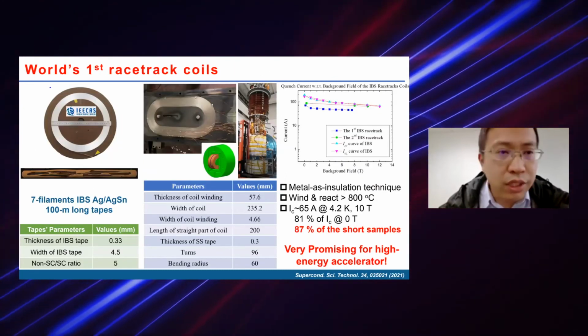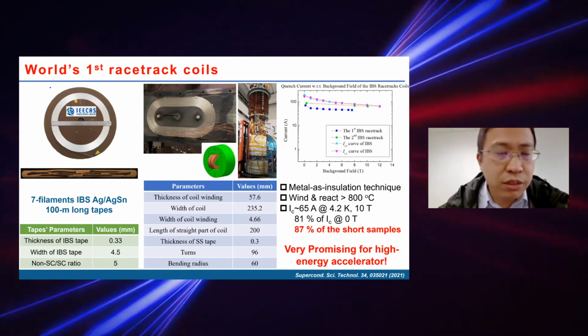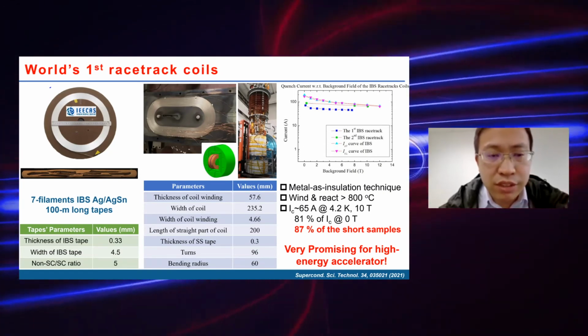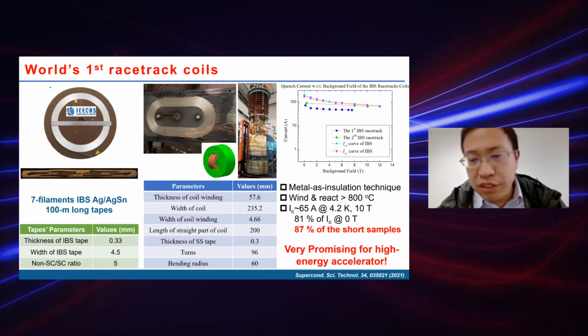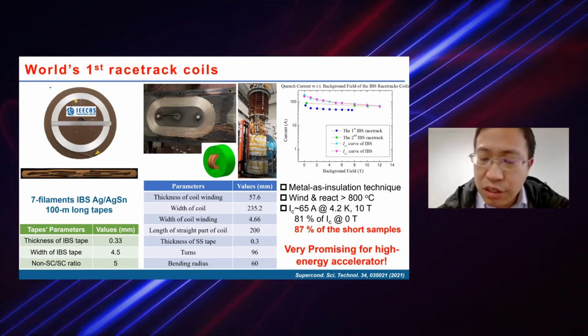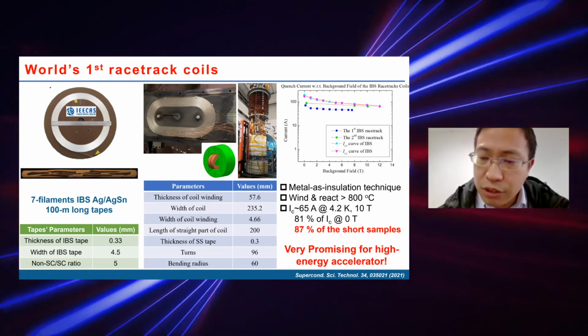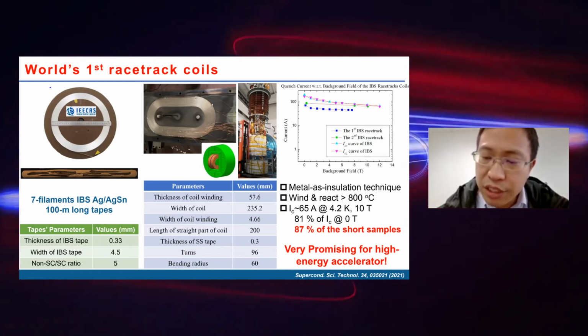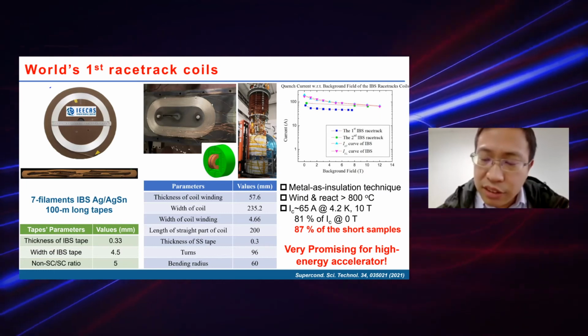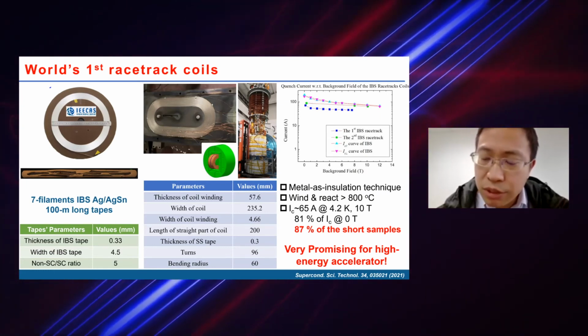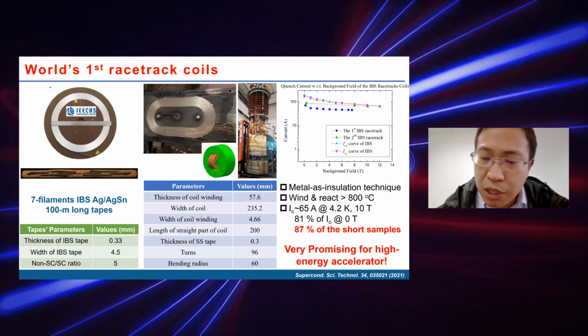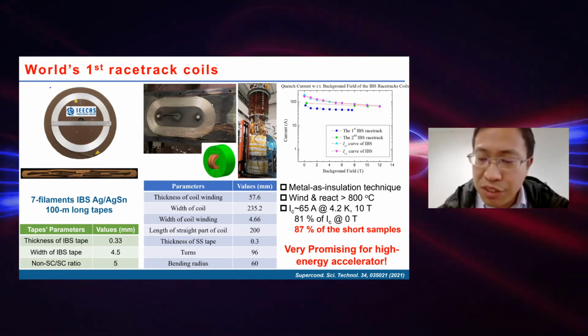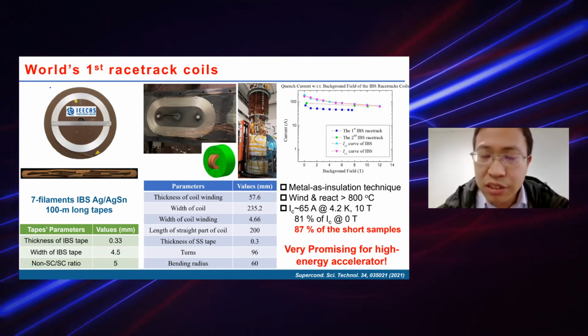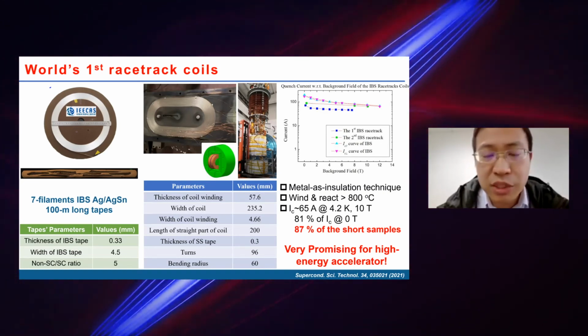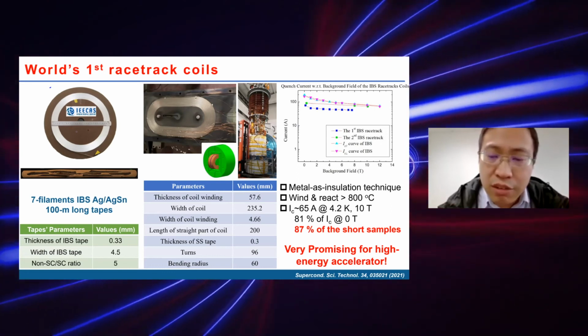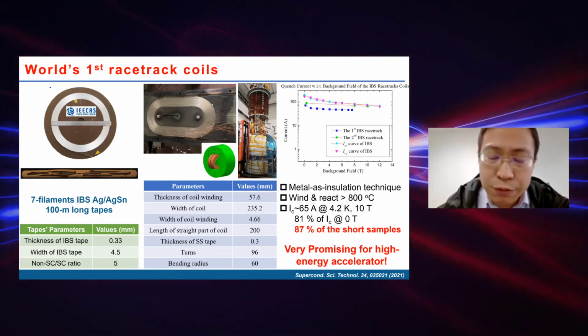And here we use 100 meter long tapes to fabricate the world's first racetrack coils. By using the metal as insulation technique and the wind and react at above 800 degrees, we can get 65 ampere at 4.2 Kelvin and 10 Tesla, which is about 87% of the short sample. This is very great news. And all these results indicate that iron-based superconducting long wires and tapes are very promising for high field magnets.